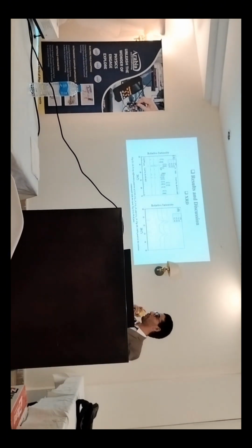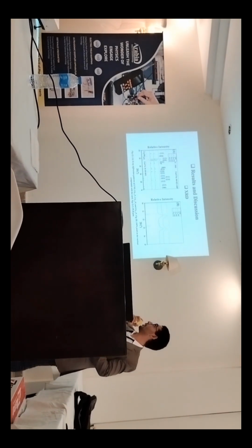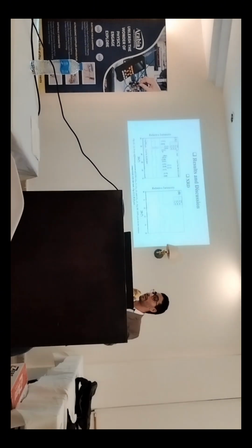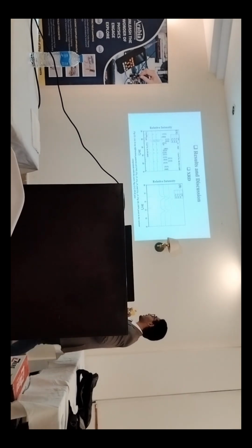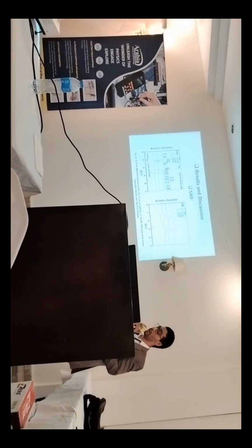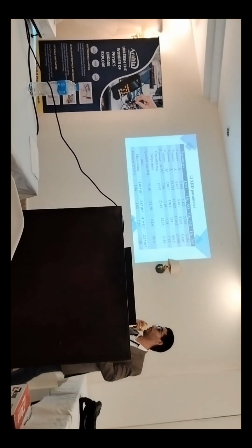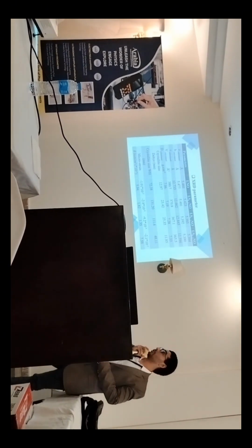So what we got from this work: we prepared the pure Ruddlesden-Popper phase, but it was slightly contaminated by some ratios of nickel oxide that didn't react. And this is obvious in this peak here. And this is the 100% peak, which changes with samarium doping. There was a broadening and shifting to higher 2 theta. These are some XRD parameters, like the main unit cell parameters and theoretical density, crystal size based on Scherrer and Williamson-Hall, and the microstrain and dislocation densities.